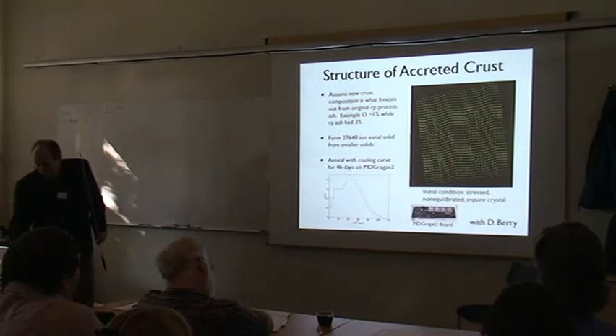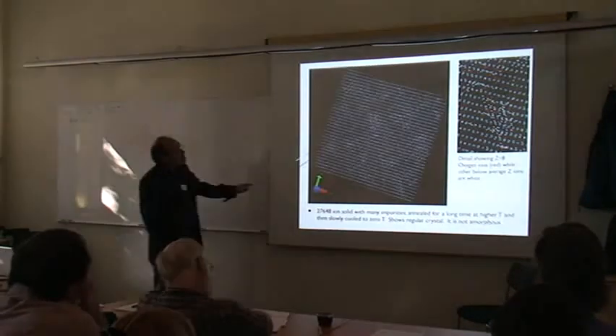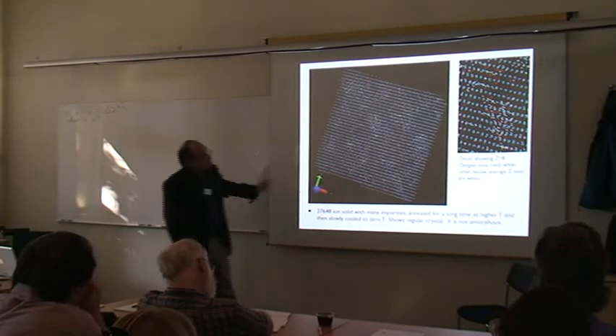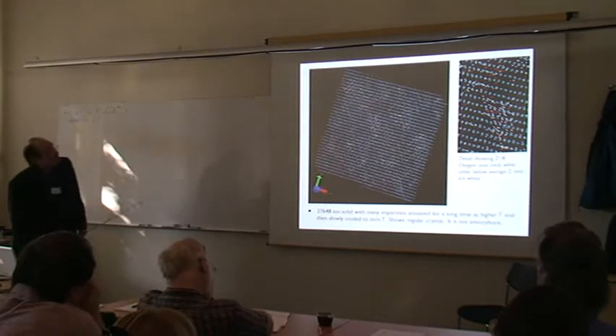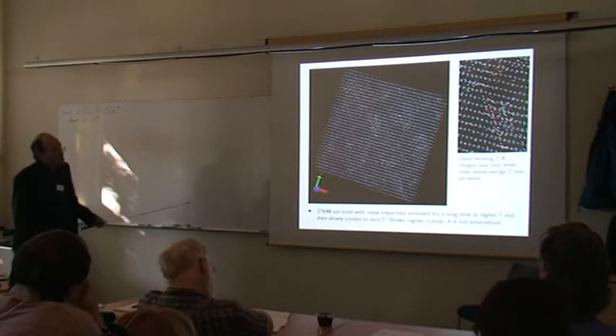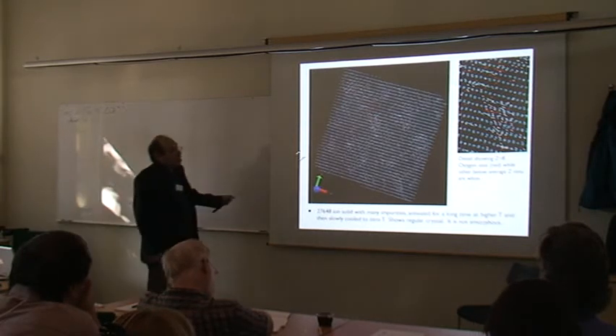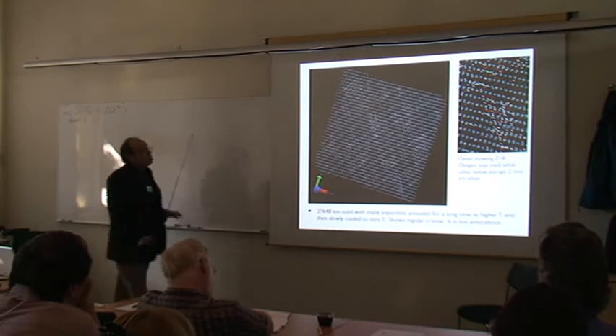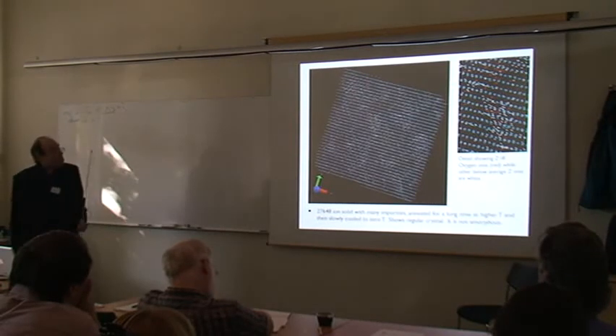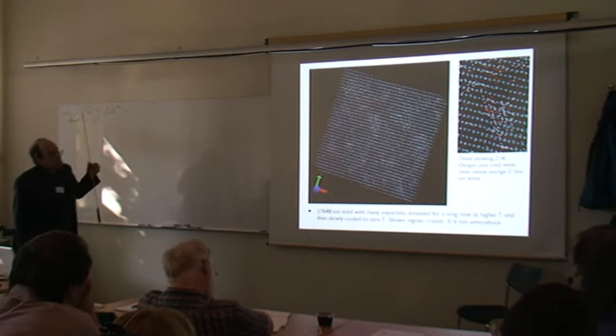And what we get is this very regular crystal. You can see the impurities, and in particular the red are the oxygen, the lowest Z impurities. So even with lots of impurities, we form a regular crystal. That's what the molecular dynamics is telling us: impurities do not give you an amorphous solid.